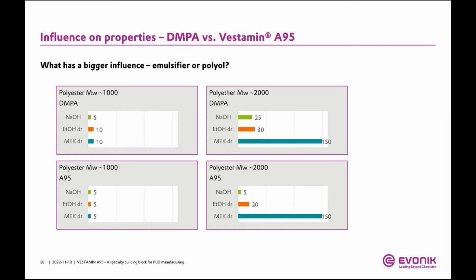So that means by taking advantage of the advantages the synthesis gives you for the A95 and the higher solids you can achieve with the A95, if you suffer at all in your properties, you can usually easily overcome this by just fine-tuning the rest of your formulation with your diol building blocks. Just tweaking them a little should overcompensate all other properties that are induced by exchanging the emulsifier DMPA to A95.